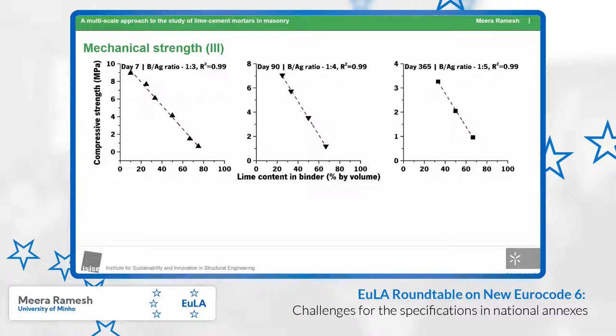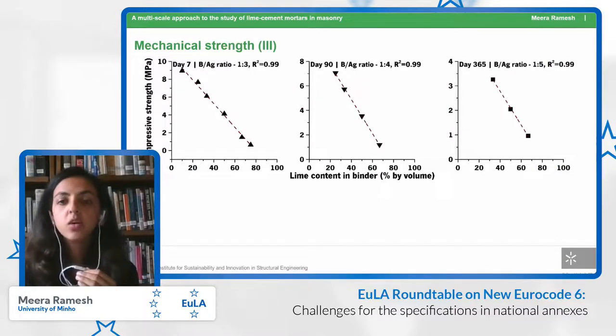Another interesting thing that we observed was that at any age, for any binder aggregate ratio, if you varied the quantity of lime in the binder, there was a way to estimate the strength of the mix because the relationship was linear. So here you have compressive strength on the y-axis and the amount of lime in the binder on your x-axis. The first graph is at 7 days of age for a binder aggregate ratio of 1:3. The second one is at 90 days of age. And the third one is at 365 days of age for a binder aggregate ratio of 1:5.